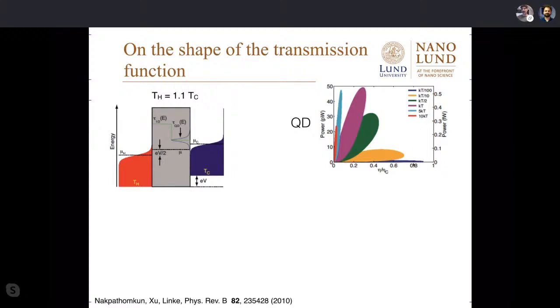And we lived down here. We were able to get some 70% of Carnot, meaning we got very little power. Now, you can get more power by opening up your resonances by making the coupling stronger, but you lose efficiency very, very quickly. So for a quantum dot, these tails, in particular the low energy tail here, are really leaky for cold electrons that then go back.